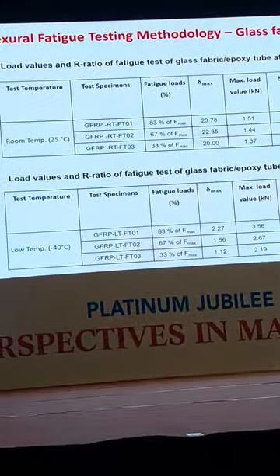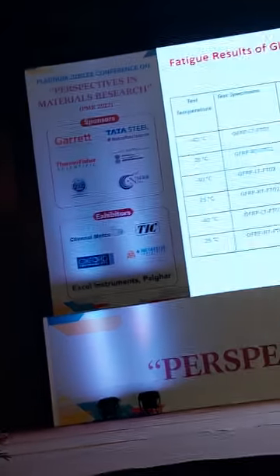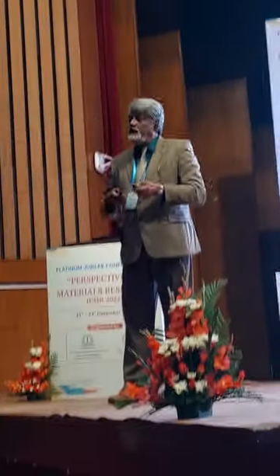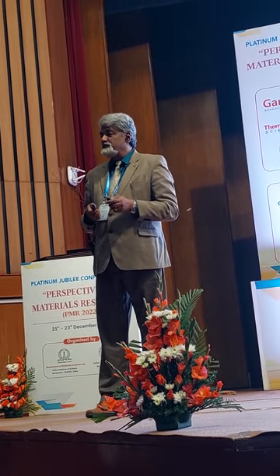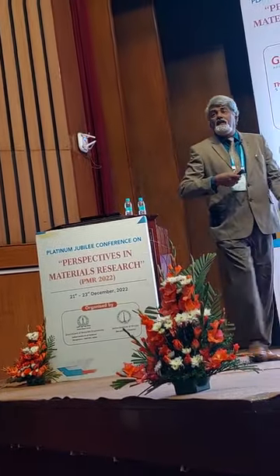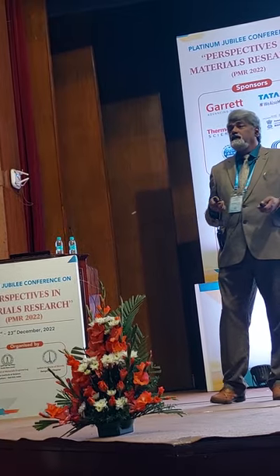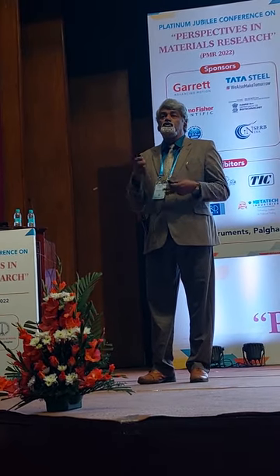For the fatigue life at 83% load, the glass epoxy beam result was poor — steel always performs better, and we are not yet ready to use glass epoxy as an anti-roll bar material. However, at 67% or 33% load, good fatigue life is achieved, reaching one lakh cycles. The 10⁵ cycle target reflects the automotive warranty standard of approximately three years of safe service life.